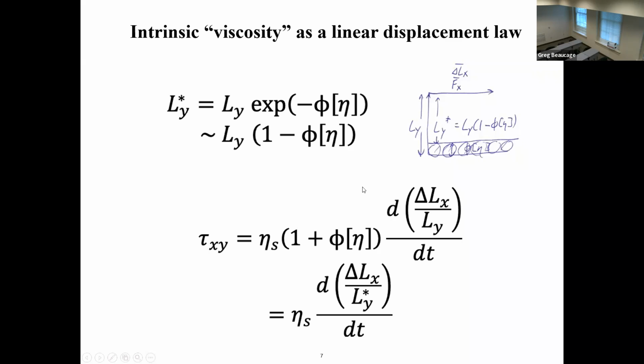And if it's 3D, you get power 0. So 3 by 3 is 1, minus 1 is 0. So you get molecular weight to the 0. So this doesn't depend on mass if it's a sphere, because it's just a displacement. The sphere is going to take up the same displacement. It just matters what the concentration of the spheres is. They'll do the same displacement. Solid objects will just fill it like bricks. So you don't need to worry about the dimension of these objects at that point. So it all kind of works out nicely